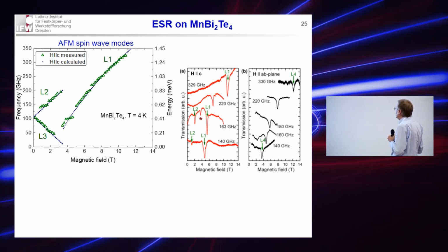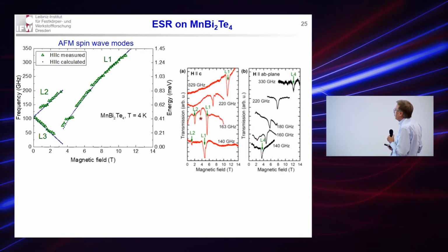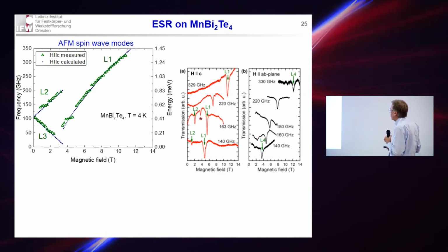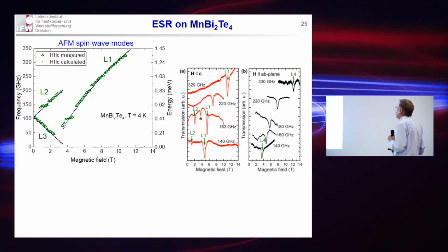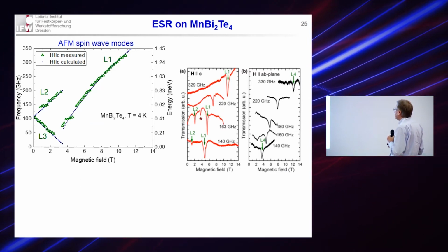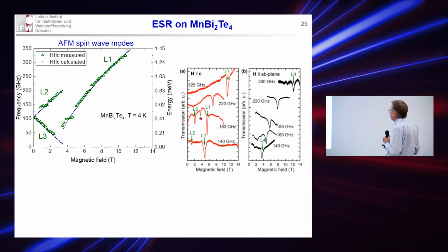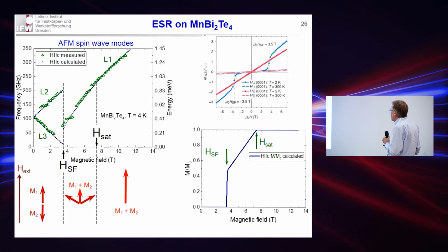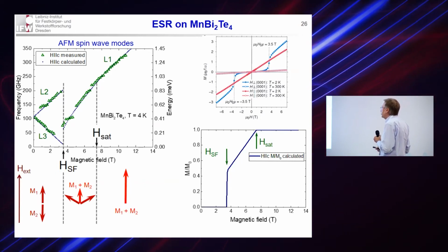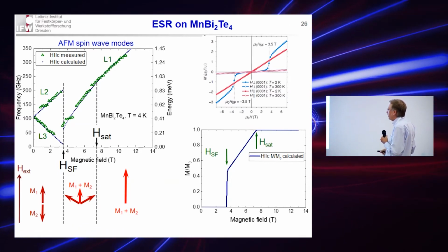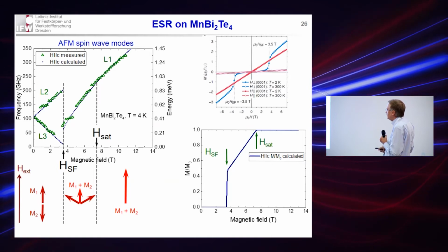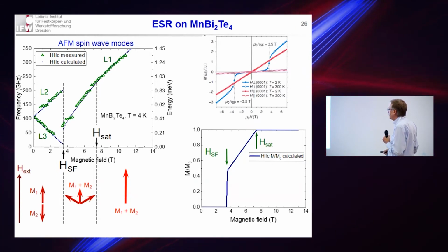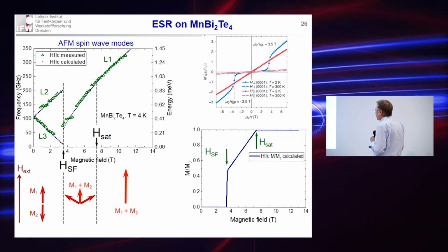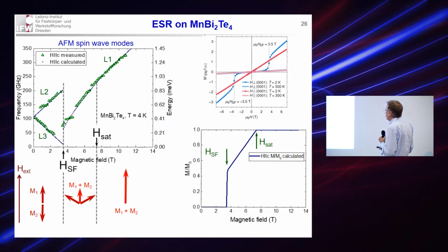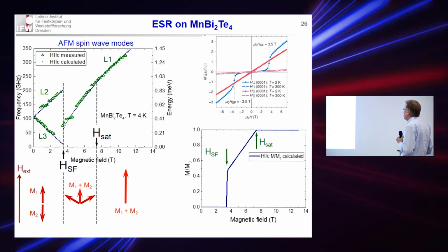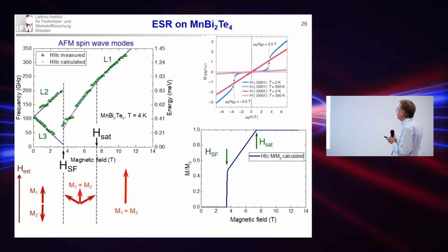So it's not a single line, it's many resonant lines which disperse differently in the magnetic field. One mode increases in energy, the other decreases, so they collapse, and then it forms another branch which has a non-linear field dependence. This is what we measured for the out-of-plane direction of the external field. Actually, we can also understand what's going on here, at least qualitatively. These would be the two typical excitation modes for the two sublattices of the collinear antiferromagnet. One precesses in phase, the other out of phase. One increases in energy, the other decreases. Then at a certain spin flop field, they flop into the perpendicular direction, and now they all precess in phase, and finally they reach the forced ferromagnetic state, forced by an external magnetic field.